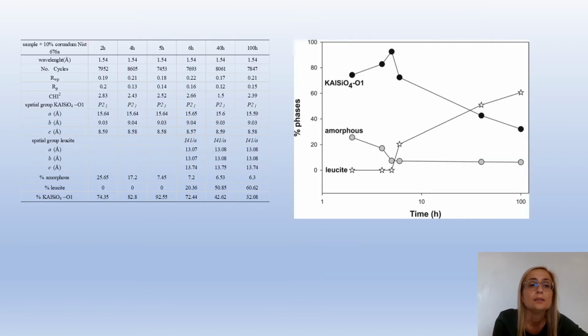Here we present the observed and calculated profiles and different plots for KAlSiO4-O1, leucite and corundum NIST 676A for the samples at 2, 4, 5, 6, 40 and 100 hours. In this table, the cell parameters for KAlSiO4-O1 refined with the monoclinic symmetry and of leucite refined with the tetragonal symmetry are reported together with the results of the QPA analysis. Cell parameters for both KAlSiO4-O1 and leucite remain constant within error as a function of the experimental run times.